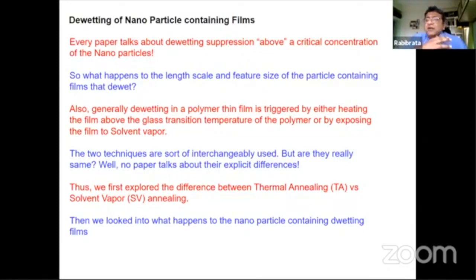So whatever the community knew was, yeah, in solvent vapor annealing mediated dewetting, there is a bit of swelling. So the actual film that is dewetting is probably a little thicker, and that's why you get a little larger droplets or larger features. And you see very fast dewetting as compared to thermal dewetting. Then the general belief was that, yeah, probably because the solvent molecules are penetrating, there is a significant drop in the viscosity, and that is probably playing this effect.